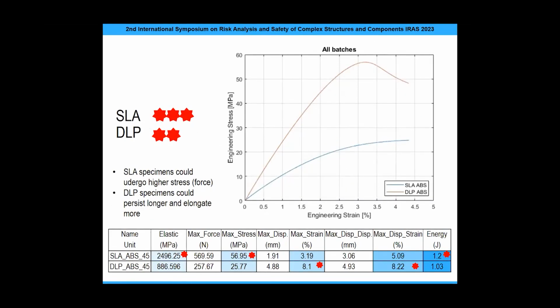In conclusion, generally, we can say that the same material, ABS-like, when used in a different additive manufacturing technology, shows different appearance and different mechanical properties. The elastic modulus is quite a bit higher for SLA-made specimens, and the maximal stress is also higher for SLA material. And the energy is higher, so it can absorb more energy if we make specimens on the SLA machine. But the DLP made specimens can strain more, and the elongation to break is higher. So as a conclusion, the SLA specimen could undergo high stress, and the DLP specimen could persist longer and elongate more.